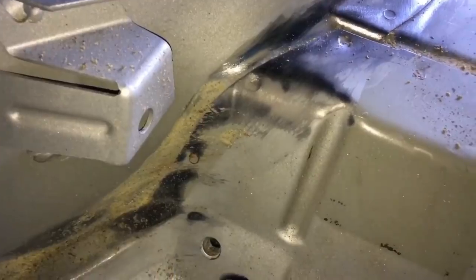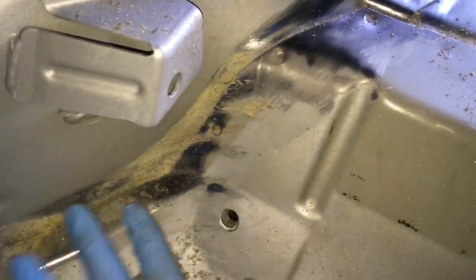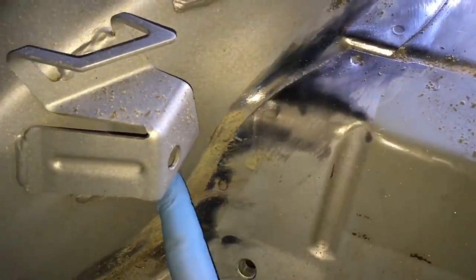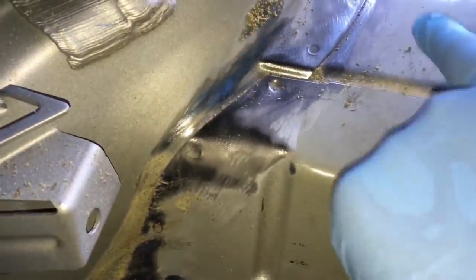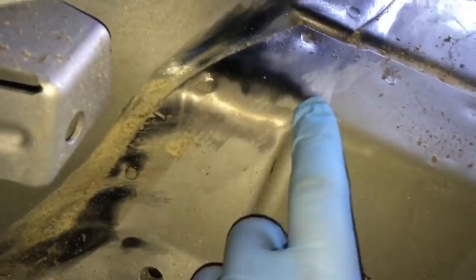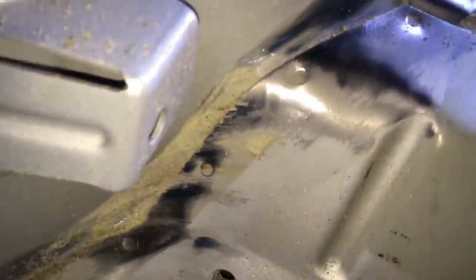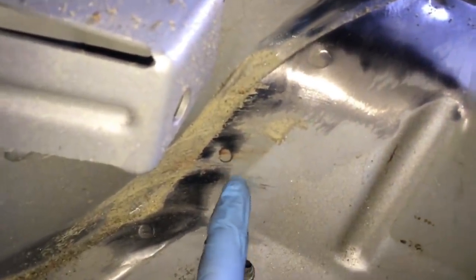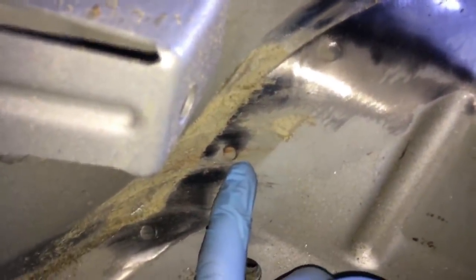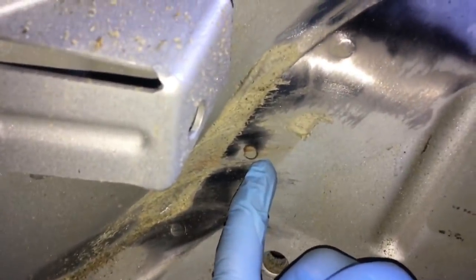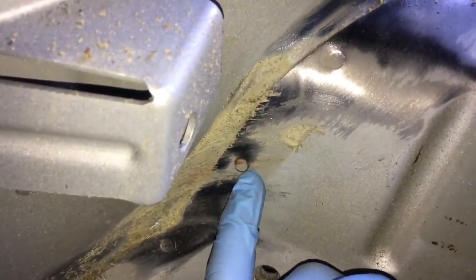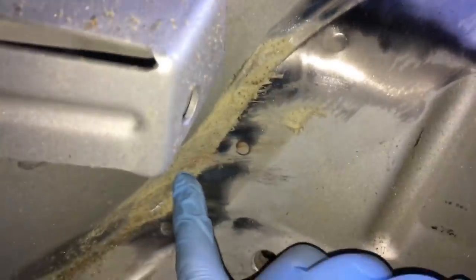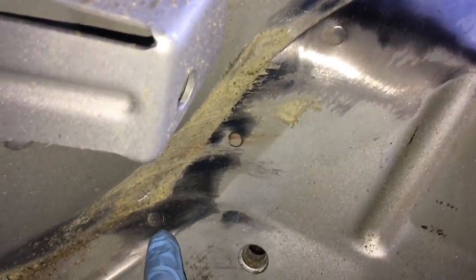We're finding some movement on spot welds on the seat panel. Here's the rear seat panel where it laps onto the mid chassis legs and then over onto the rear axle carrier panel up here. There's a few spot welds, 1, 2, 3, 4 at least on this slope holding it down. And we've got one here which is showing, it's probably not cracked all the way around, but it's definitely got flex or some form of crack around it because there's corrosion in it, and this was covered in thick seam sealer. This spot weld was fine.